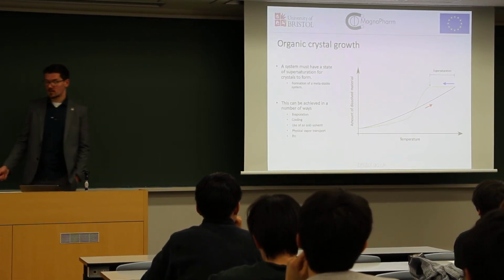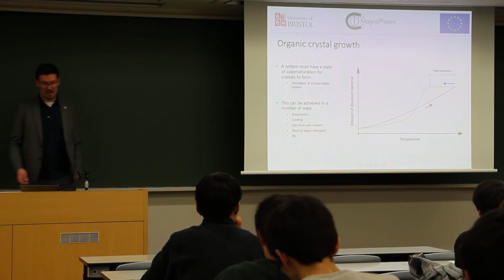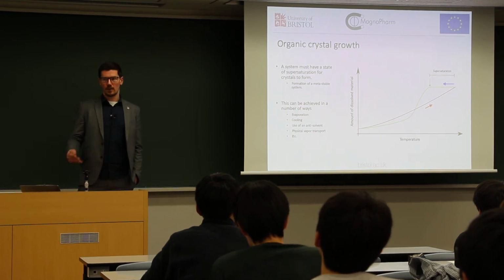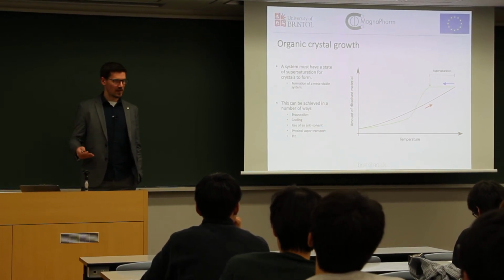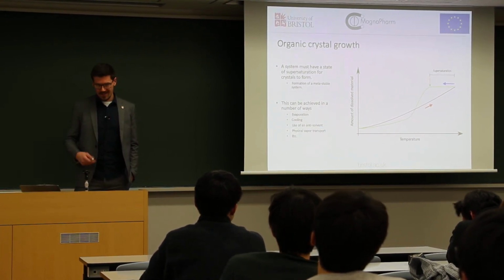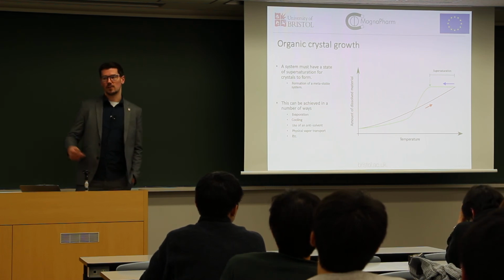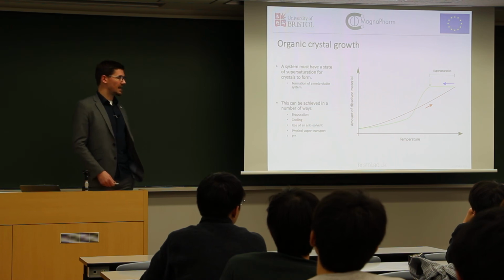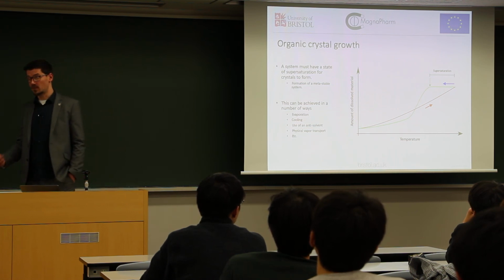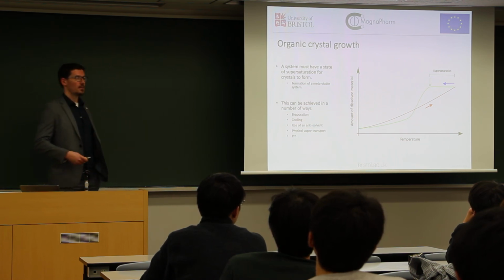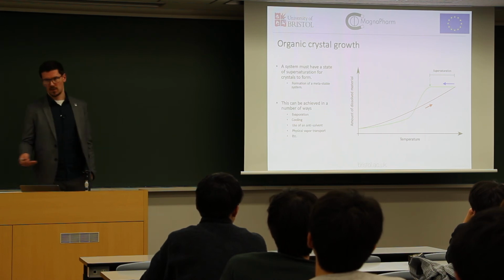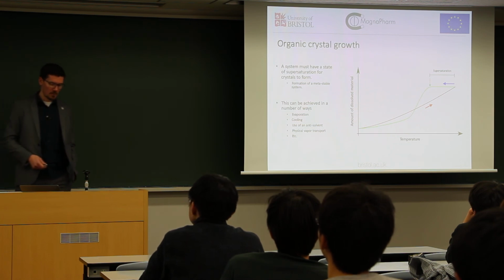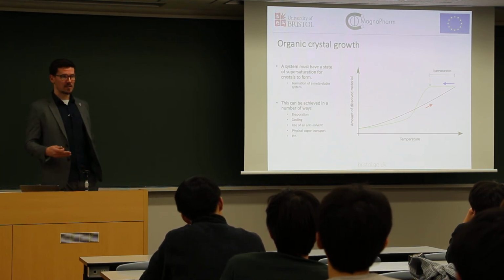So organic crystal growth is basically a function of making a supersaturated system, be that in solution, or in physical vapor transport. Typically, a crystallization experiment is you dissolve your solute in a solvent, you then increase the supersaturation. It can be done in a number of ways. You can have an evaporatively driven crystallization where you let the solvent come off bit by bit, and that increases the supersaturation here.